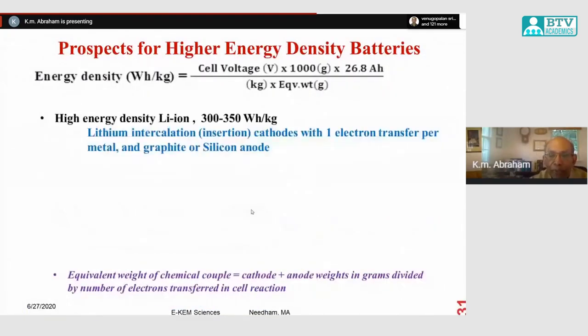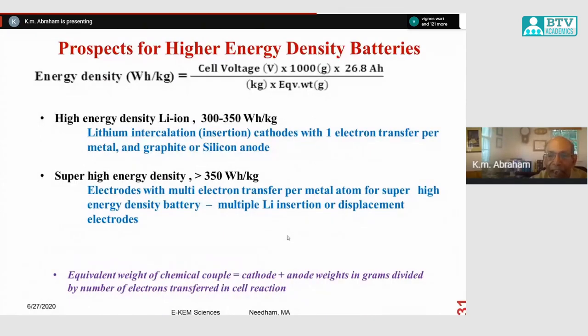All right. So what are the prospects for future higher energy density batteries? With a lithium-ion intercalation electrode with one electron transfer per metal, as in lithium cobalt oxide, one lithium moving, one electron inserting and extracting from it, the maximum you can get is around 300 to 350 watt-hours per kilogram. If you want super high energy density batteries greater than around 350, you have to have multi-electron transfer per metal. You have to transfer more than one electron per metal in a cathode material for an insertion electrode reaction.